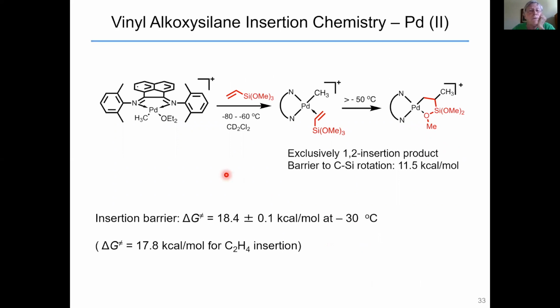Well, again, if you take the methyl ether complex and expose this to trimethoxyvinylsilane, you can see the pi complex, and then you can watch this undergo migratory insertion at about -50 to generate the chelate. It's exclusively a 1,2 insertion product. This is a fairly weak interaction. The barrier to rotation around this silicon carbon bond is about 11 kilocalories per mole. The insertion barrier is a little over 18, which is very close to the ethylene insertion barrier, just about half a kilocalorie difference. So the vinyl trialkoxysilane inserts with about the same barrier as ethylene.